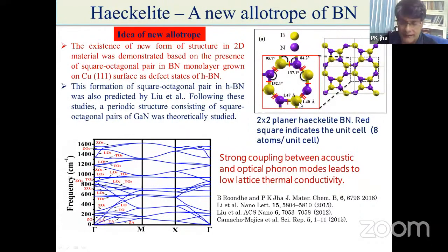Haeckelite is another allotrope made up of boron nitride, right? It is basically, after applying the strain, a square octagon pair in hexagonal boron, which was predicted long back, and of course that was also observed in gallium nitride, and this is the dispersion curve, right? And as I have already mentioned, we observed that a strong coupling between acoustic and optical phonon modes leads to low lattice thermal conductivity. And if you remember, I said while discussing the quest for lower thermal conductivity that if there is a coupling between the acoustic and the optical phonon, that is good for low lattice thermal conductivity.